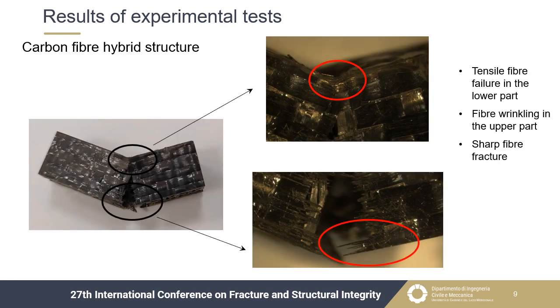Some images of the fractured zone were taken to inspect the fracture mode. As concerns the carbon specimens, the fiber failure was observed only in the lower part of the specimen itself, while fiber wrinkling was noted in the upper zone, just below the loading nose. The most interesting thing to highlight is that a sharp fiber fracture was observed in the lower part.